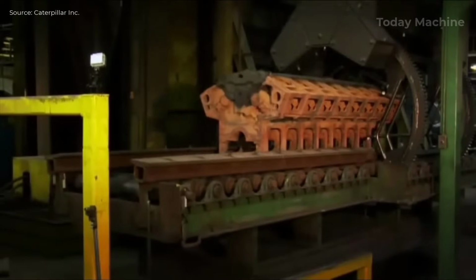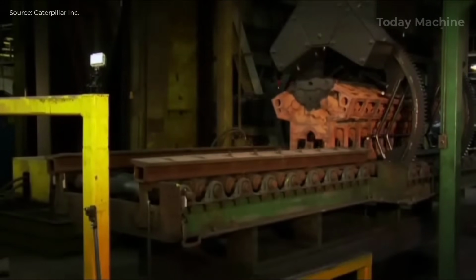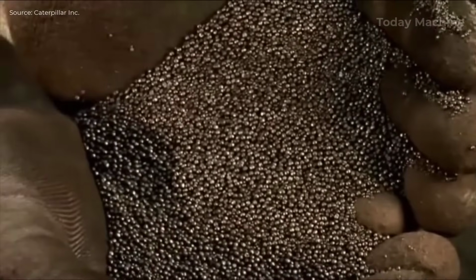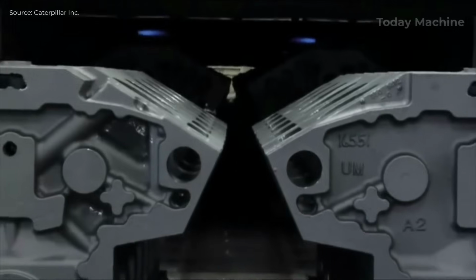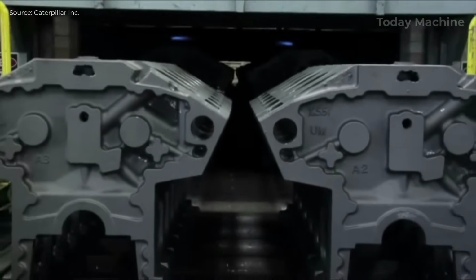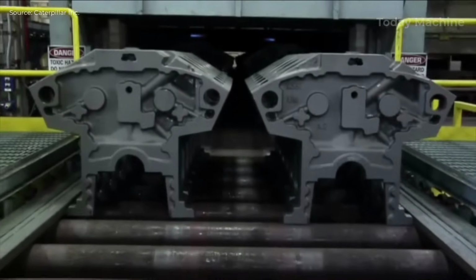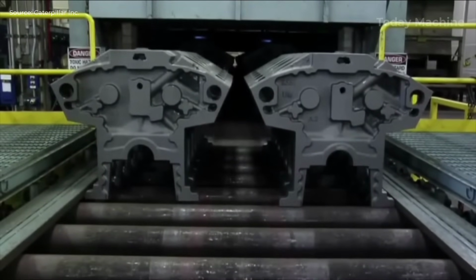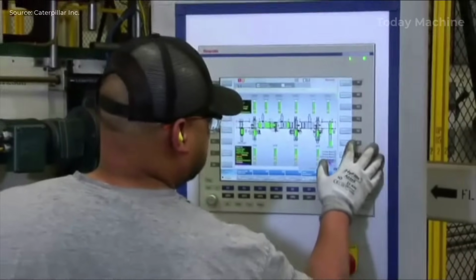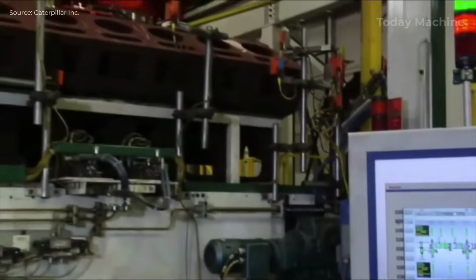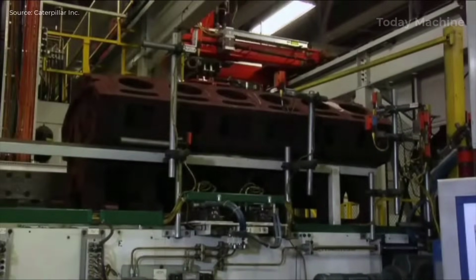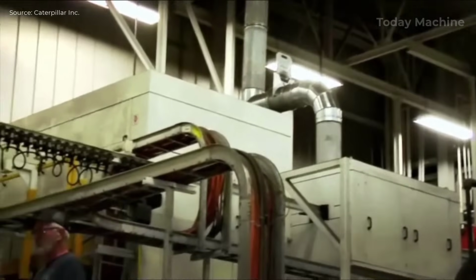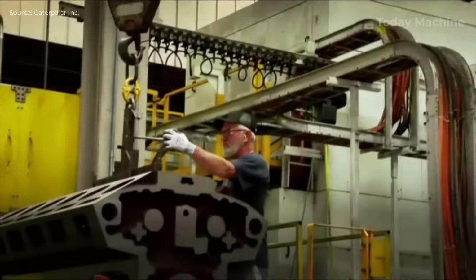After the iron cools and solidifies, the casting is removed from the mold, and any remaining sand is blasted away using steel pebbles in a process called shot blasting. This cleans the casting, revealing the rough engine block. To relieve internal stresses caused by the cooling process, the block is then heated to 1,100 degrees Fahrenheit, preventing future cracks. Finally, the block undergoes a machining process called deburring, which removes rough surfaces and ensures the block's uniformity and structural integrity before it moves on to the final machining stage.